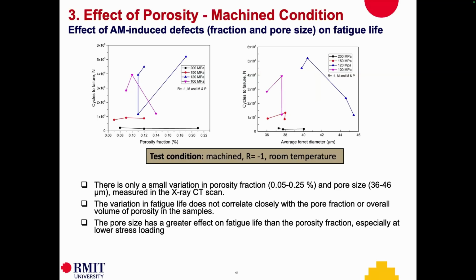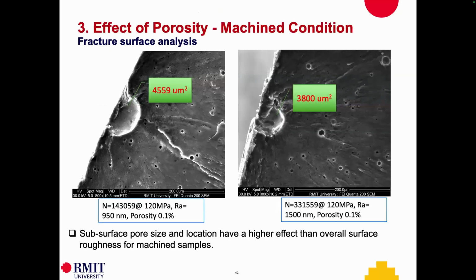The variation of fatigue life, this is a key message, doesn't correlate closely with the pore fraction or overall volume of porosity. The pore size we found to have a greater effect on fatigue life than porosity fraction, particularly at lower stress loading. So why is all this happening? What is the problem? What are we missing here? What's the missing link?